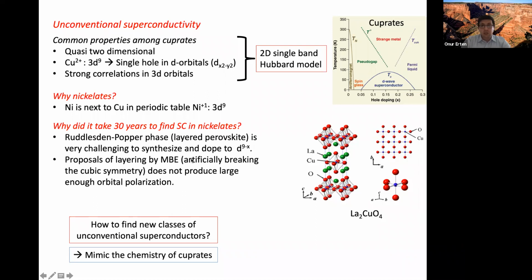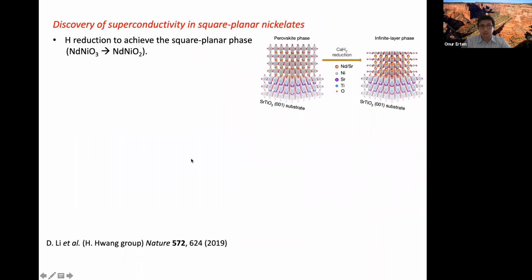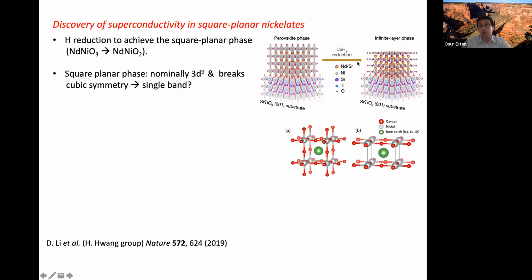All right, so now we come to 2019. Harold Hwang's group from Stanford were able to grow the perovskite phase, neodymium nickel O3, as thin films using MBE on top of strontium titanate, and using a technique called hydrogen reduction, they were able to mainly get rid of the apical oxygens.